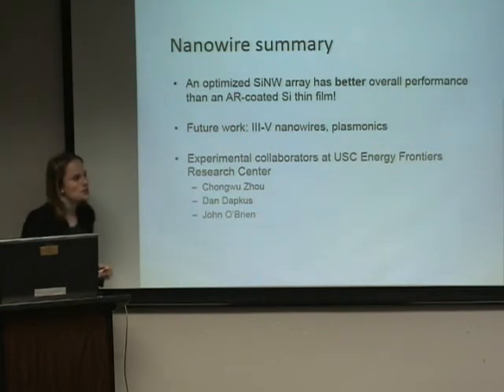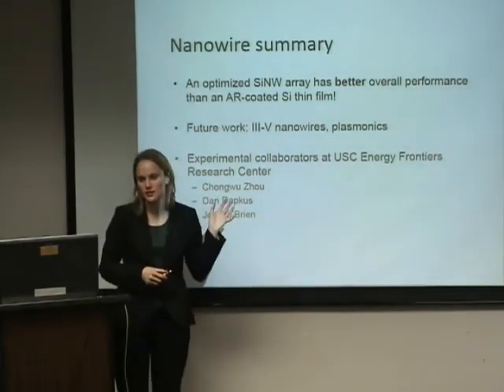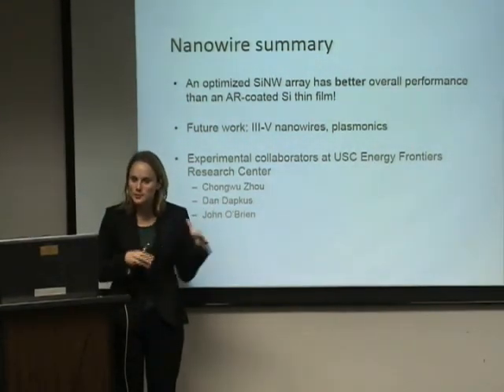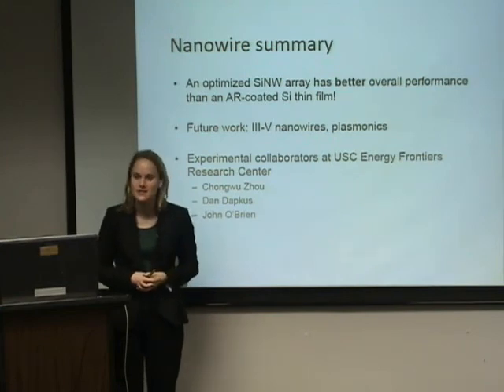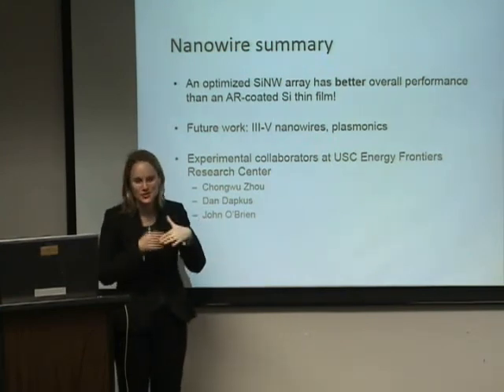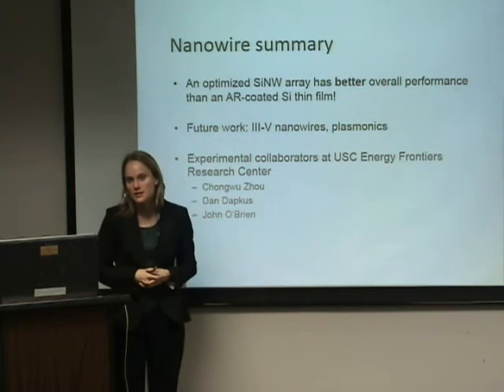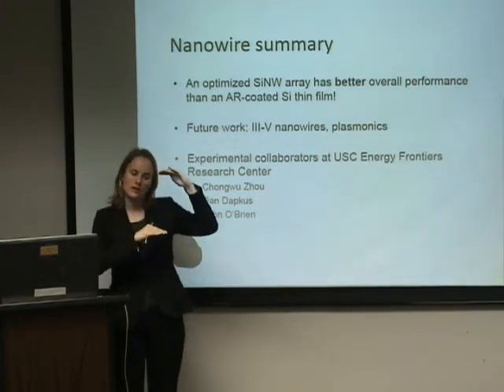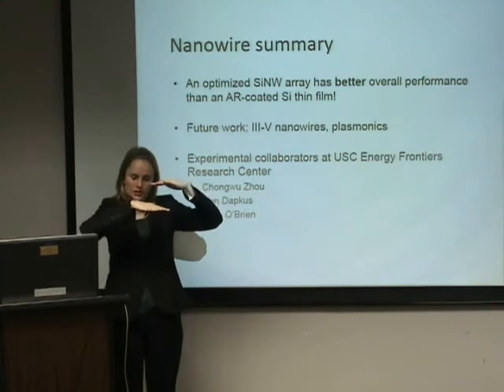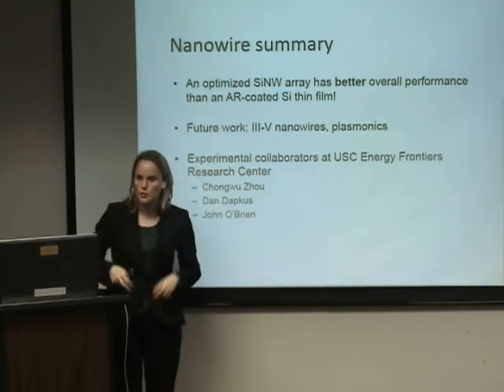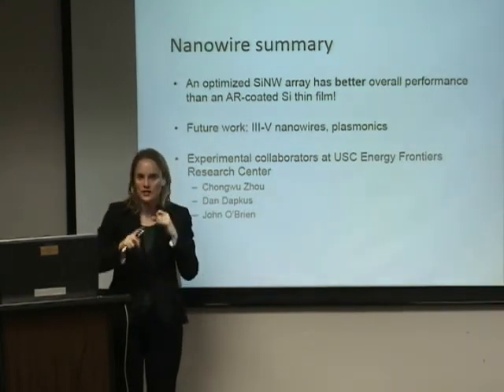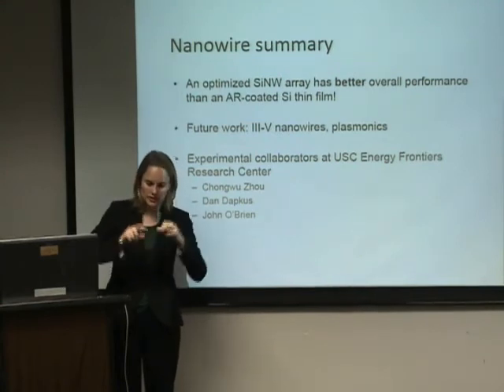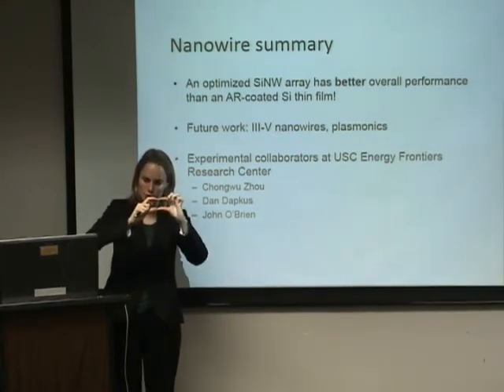So length is also important, and this conclusion that it's better than a thin film will probably not apply over all lengths. And my student is now trying to map out that dependence. The key physical feature is that for these thin film structures, the problem that we're trying to overcome, one is the reflection. The second one is that the thin films are so short that not all the light gets absorbed.